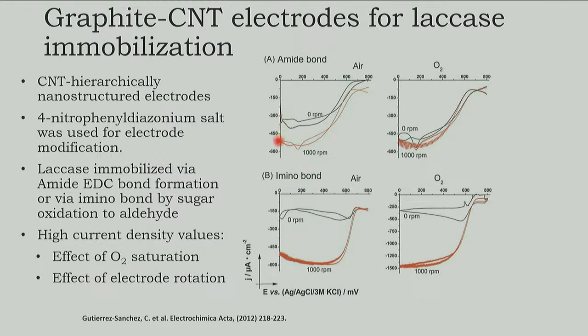The currents increased from the 200 that we had before to 500-600 here. Here we realize that there is an issue with the oxygen supply, because the enzymes are consuming it, and oxygen is not very soluble in these solutions. So more or less this is what we can get. You can see in air, when we put in extra oxygen, the currents go up. And when we make a 2-step immobilization, instead of directly making an amide bond, we make a partial oxidation of the sugars on the surface of the enzyme to open them and make aldehydes. Then they join the amino groups, forming a Schiff base, and then it is linked, because most of the sugar residues are in the proper orientation, favoring covalent bonding later. We can see that the current increases to like 1.5 milliamperes, which is more than 5-6 times the values in the earlier work.